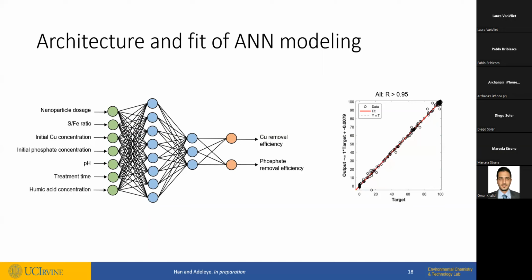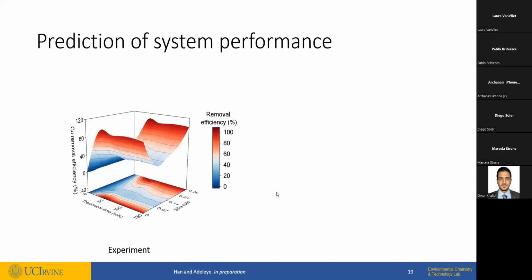In any case, this is our architecture. So these are all the input parameters: nanoparticle dosage, the ratio of sulfur to iron, and the contaminant concentration, and so on. And another thing I like about this particular work is we were able to simultaneously predict the efficiency of the removal of both copper and phosphate, which is different from predicting one at a time.